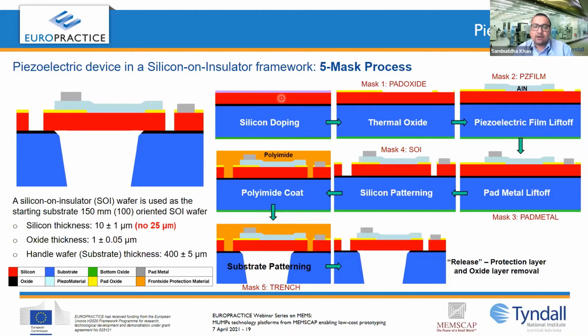It starts, as I have already mentioned in the SOI MUMPs case, with the silicon being doped using PSG deposition, and then the first mask, called the pad oxide. In the pad oxide step, you grow a thin thermal oxide of 500 nanometer, and then you etch the thermal oxide using this pad oxide mask. Once the oxide is selectively removed, a blanket layer, the piezo film mask, is used to deposit the piezoelectric film that is made of aluminum nitride, and it's also 500 nanometer thick. And this is done using a lift-off process.